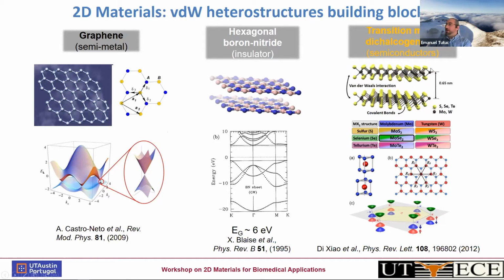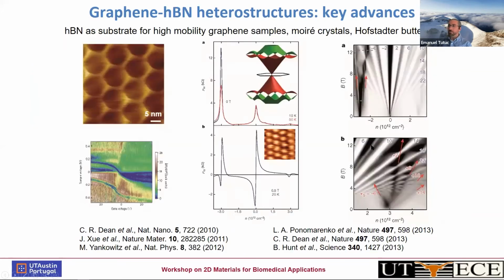And then there is this family of semiconductors called transition metal dichalcogenides, which have a chemical formula MX2. M is a transition metal, X is a chalcogen, that would be a group 16 element. The transition metal could be, in this particular case, a group 6, molybdenum and tungsten are the most often used, and they form a semiconductor. And in the monolayer limit, as Shintong very nicely illustrated, it's a direct gap semiconductor with the band extrema again at the K point, the corners of the Brillouin zone, which is also hexagonal in this case.